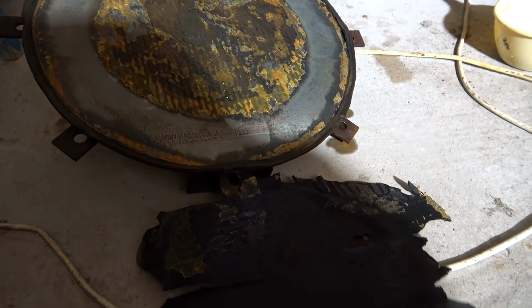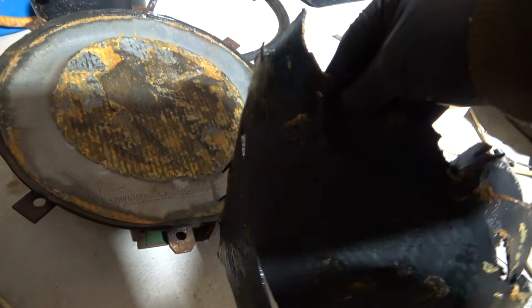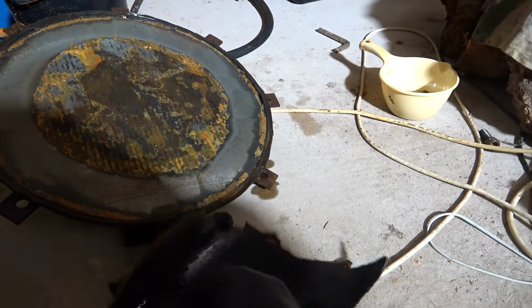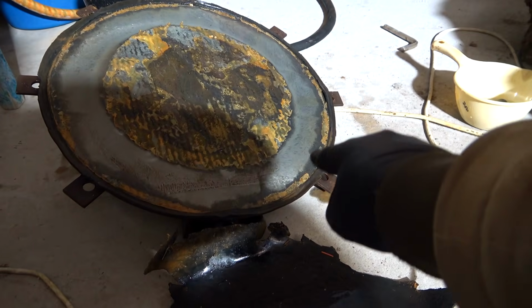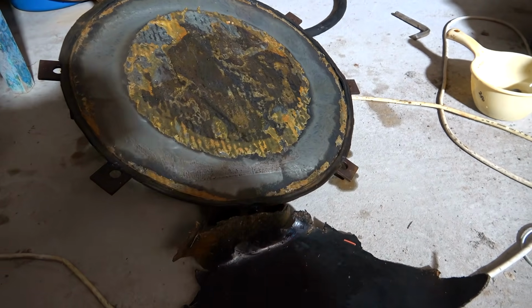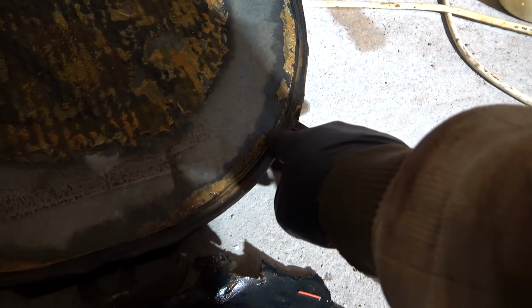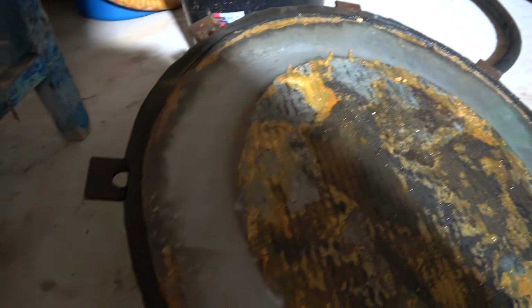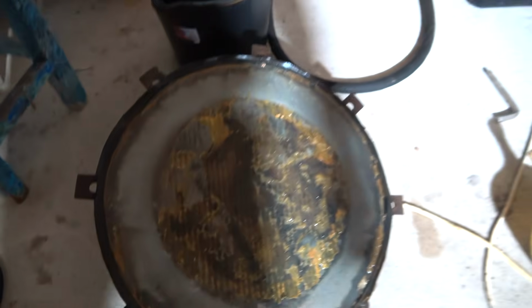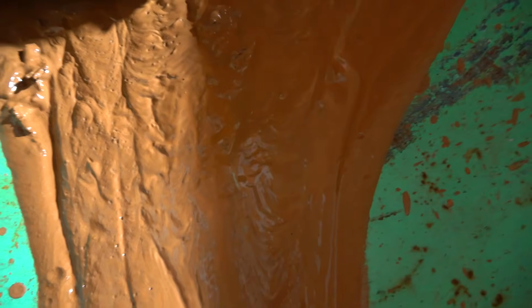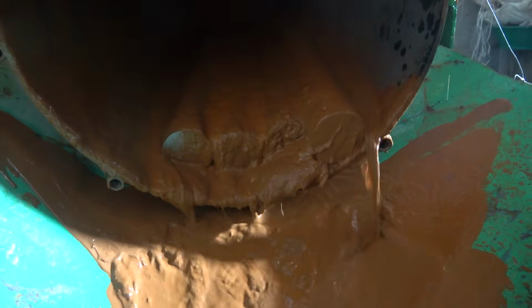Dear viewers, that's how the rubber gasket from the lid was torn with metal rods, only the rim along the edge remained. I expected to use this crusher as a ball crusher, but the results showed that metal rods can be used. The contents are removed very easily, the lid is closed, new material is loaded through the hatch and turned back on for grinding.